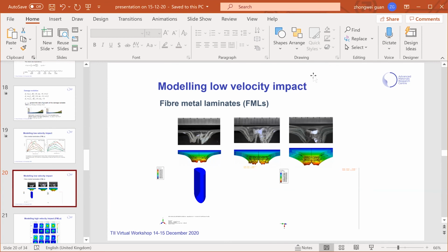How important is it to model the contact or the adhesive behavior between the laminates and the composites? That's very, very important. You have to simulate this interface interaction properly. Due to the time limit, I didn't have time to explain here. We use a cohesive layer, which is available in the commercial code, between the aluminium alloys and the composite. You can also use a cohesive layer between composite plies, but if you have many plies, the CPU time is too much. Very difficult to handle.